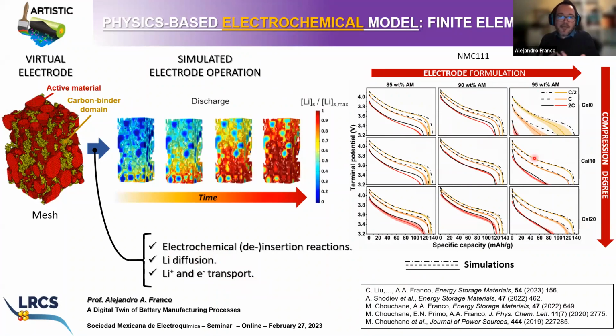And this is, I believe, also another way of validating the manufacturing simulation framework, because that means that the electrode microstructures you are predicting by using different formulations and different calendering degrees allow you to predict galvanostatic discharge curves in good agreement with experimental ones. This is a paper that we published also this year in 2023.